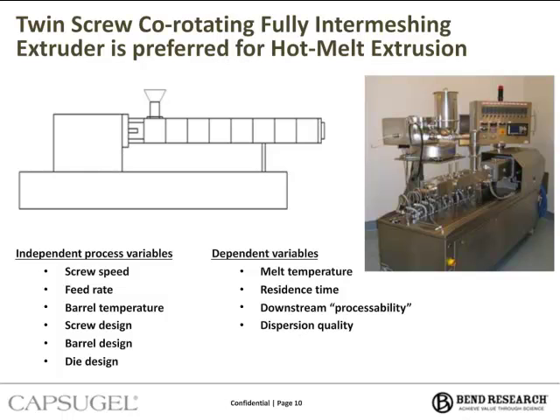So the continuous independent process parameters, and by continuous I mean they can be changed on the fly, are screw speed, feed rate, and barrel temperature. Some non-continuous variables are screw design, barrel design, and die design. And then finally, some of the dependent variables are the melt temperature, the residence time, the downstream processability of the extrudate, and the dispersion quality.